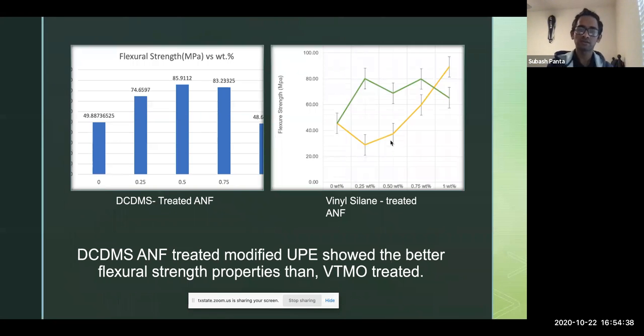So comparing the results of dichlorodimethyl treated aluminum nanofiber versus vinyl silane treated aluminum nanofiber, dichlorodimethyl treated aluminum nanofiber modified polyester showed better flexure strength properties than vinyl silane treated aluminum nanofiber. In terms of dichlorodimethyl treated aluminum nanofiber, at 0.50 weight percentage, 85 megapascal of flexure strength was obtained, but for vinyl silane, at 0.50 it is between 60 and 80 megapascal. So dichlorodimethylsilane treated is far better than vinyl silane treated in terms of flexure properties too.